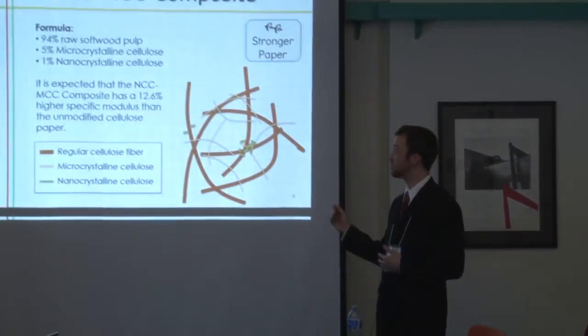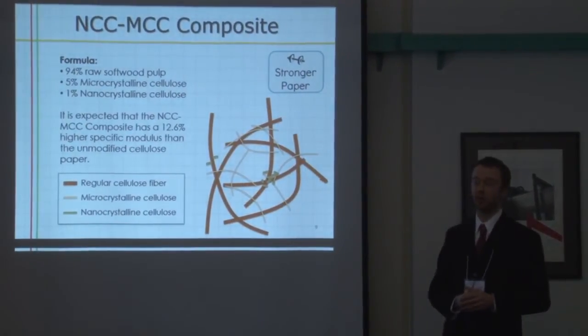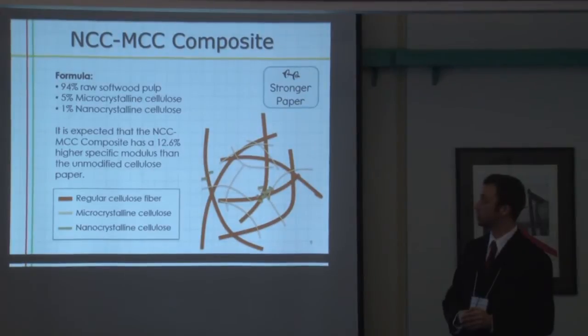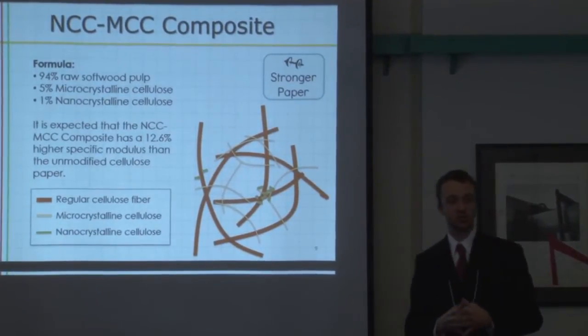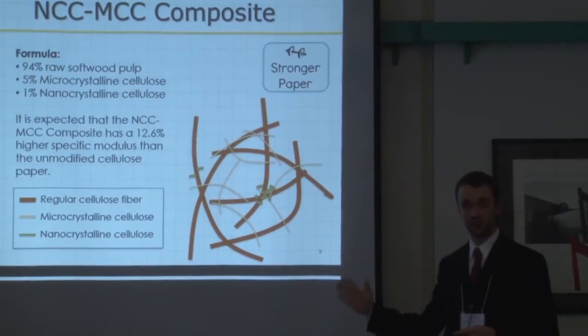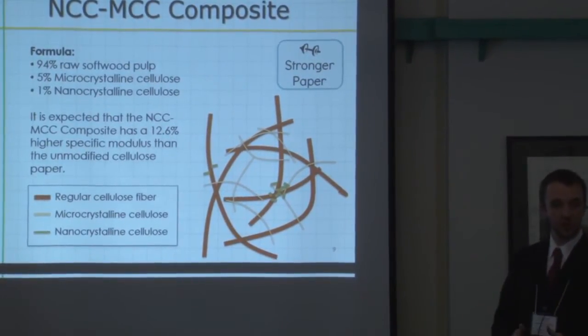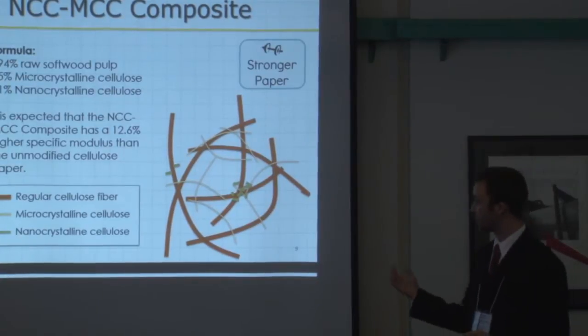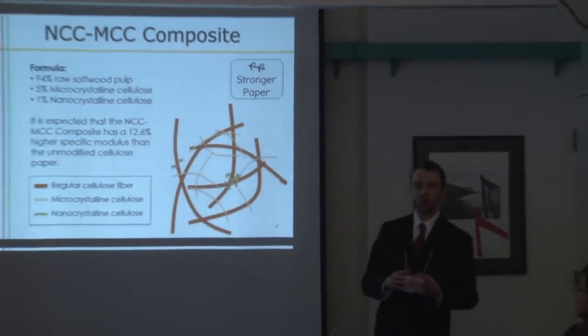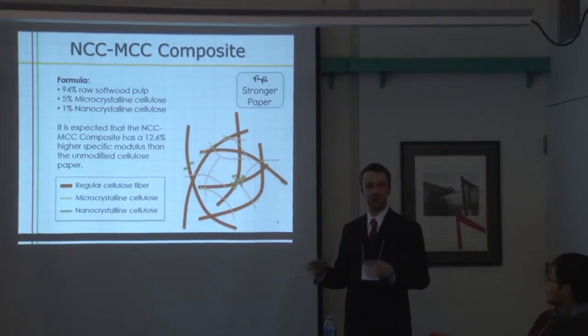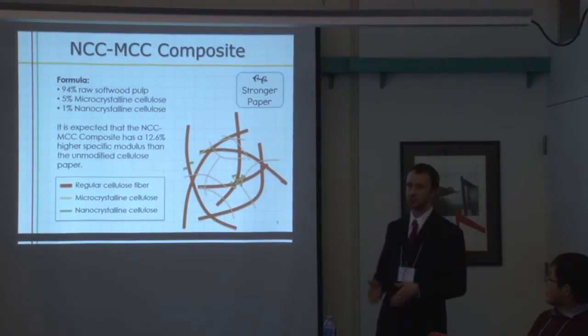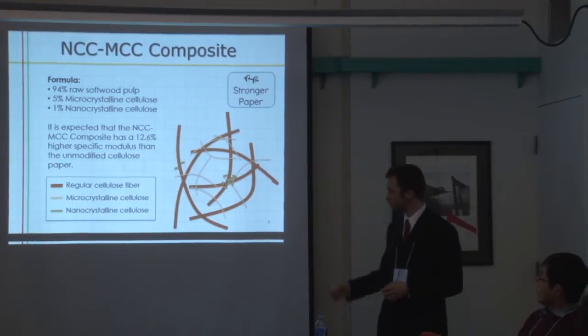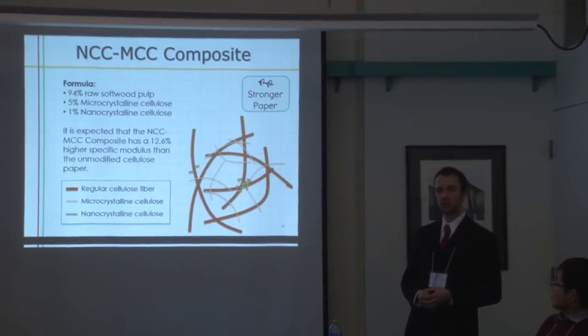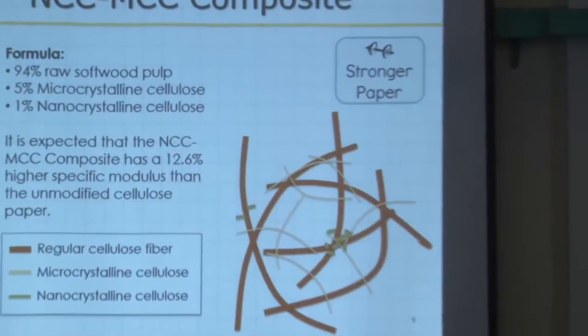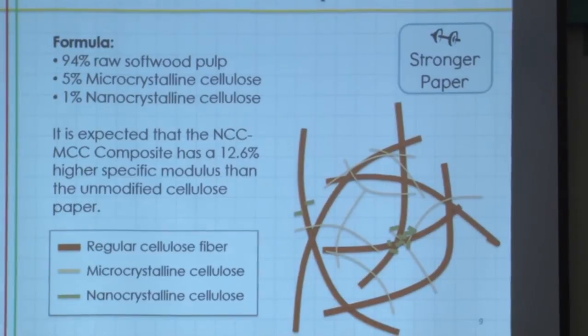for increased strength. The particular formula we used consisted of 94% raw softwood pulp, 5% microcrystalline cellulose, and 1% nanocrystalline cellulose. The reason we chose this particular formula is we believe that this would be enough additives to exhibit some sort of impact on the mechanical strength of the composite, and at the same time, according to literature review, this amount of additive is enough so that we can use mathematical models to estimate the improved strength of the composite. Our calculations suggest that this composite should have a 12.6% increased specific modulus as compared to a formula entirely made